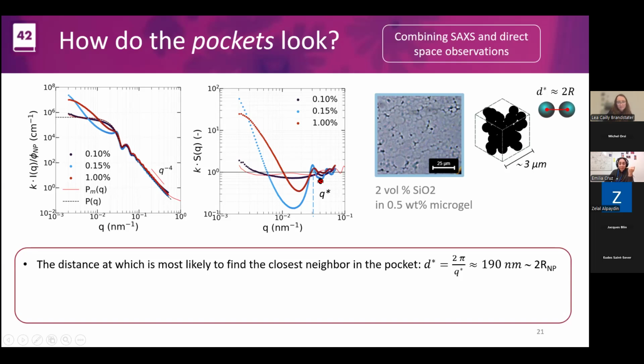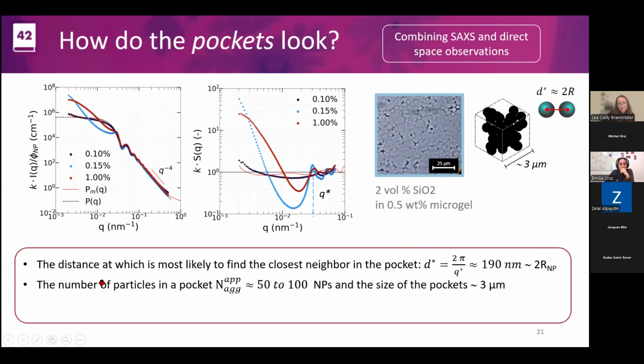So the very first thing is the distance that I was telling you, the distance at which it is most likely to find the closest neighbor in the pocket. So d star will be 2 pi over Q star. So at that particular scattering angle, we have this peak that appears, which is close, in real space, to 2 times the radius of a particle. So meaning that the particles within that pocket are almost touching each other. They are very confined. Then we see the number of particles, which is an apparent number of the aggregate, let's say, that we can compute by simply estimating what the scattering intensity here is compared to when there's just one particle. We can estimate that there are around 50 to 100 nanoparticles in these pockets.